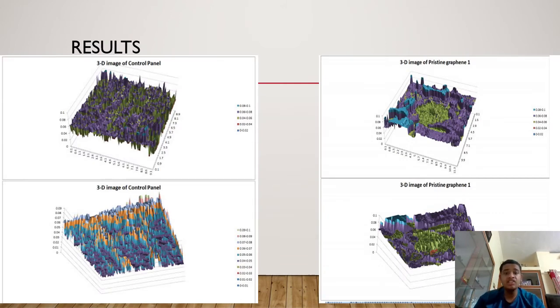So the two images illustrate the 3D view of the damaged volume observed from two different angles after a simulated lightning strike. And this was obtained using ultrasonic testing. So the color scales on the right hand side represent the thickness readings taken from the damage zone. So the image on the left shows the control panel and the image on the right shows the pristine graphene.